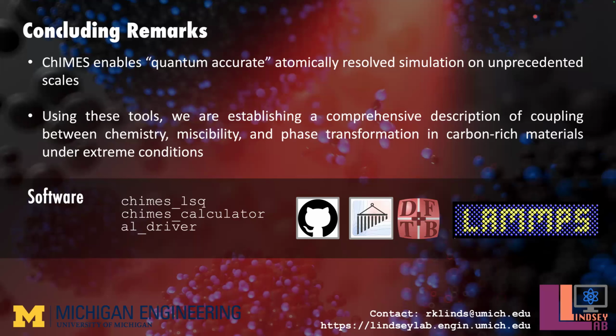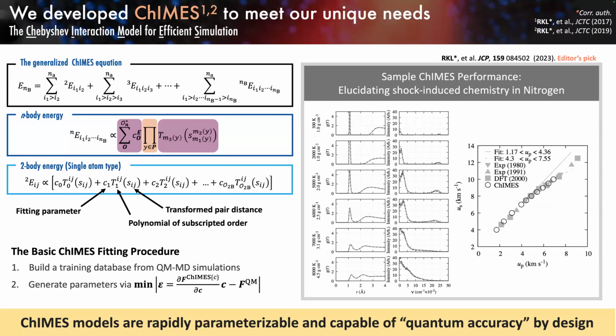My last comment goes back to your earlier chart - your charts aren't numbered, but I believe it was your quantum-informed chart showing what looked like radial distribution curves. I'll note that you showed a sharp rise, first diffraction peak around 1 angstrom, so that's not molecular. But what it likely is, based on work I've published with Alan Soper at Oxford et al., is a void distribution curve where below say 1 angstrom, at or below 1 angstrom, that may also be a very interesting parameter telling you something you may not have thought of before. Over, thanks again, good seeing you.